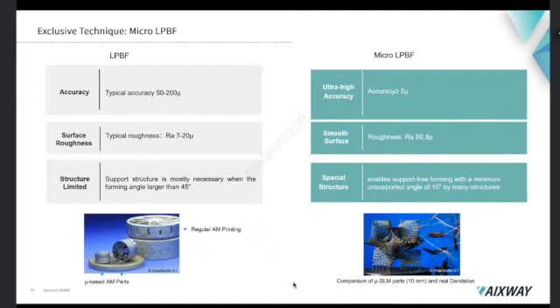And micro 3D metal printing has three major advantages compared to conventional machines. First, in terms of precision, the typical accuracy of conventionally printed parts is 50 to 200 microns. Our technology allows the laser focus diameter to reach an accuracy of 20 microns. The minimum layer thickness goes down to 5 microns due to the special powder feeding system. Printing accuracy is greatly improved. As a result, the typical accuracy of our printed parts is 2 to 10 microns.